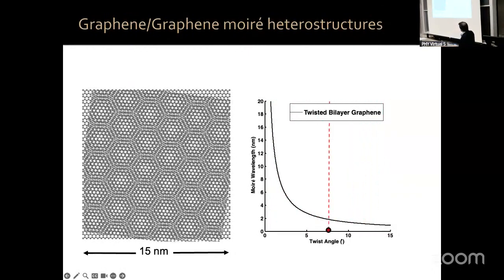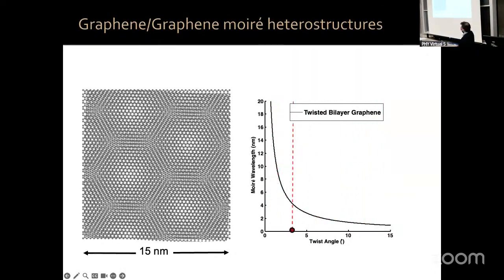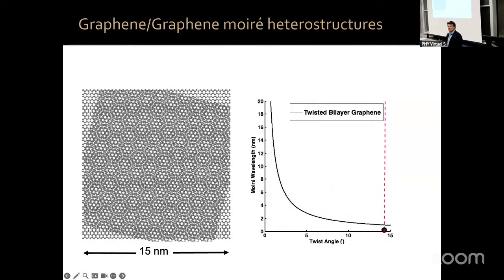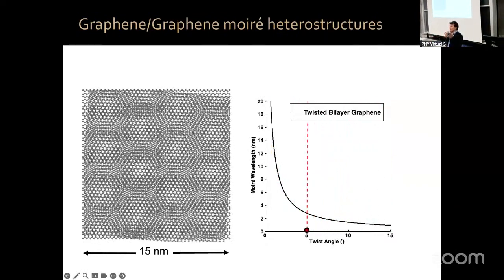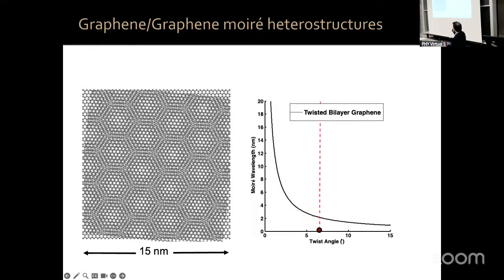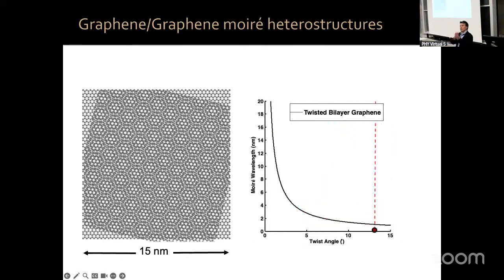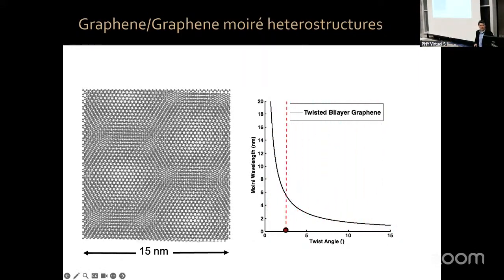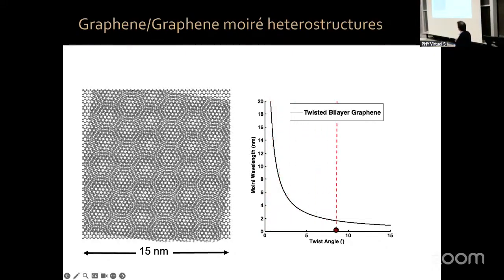Because these two lattices are identical, this can go all the way to infinity. If these two lattices were two different materials with slightly different lattice constants, there would be a saturation, a maximum moiré wavelength, even if you perfectly align them. But for graphene on graphene, it can go all the way to infinity.